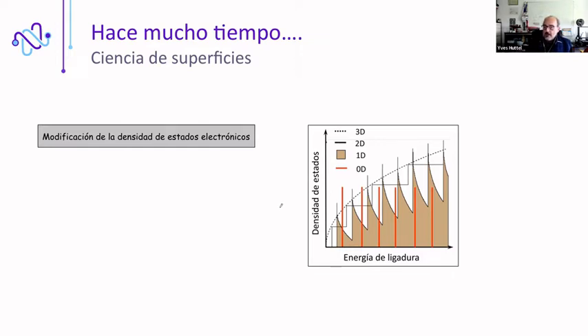And this is the key point, because as you reduce the size of your object, the density of states, which means the electrons that will participate in most of the properties of the materials, not only electronic properties, but also magnetic properties, optical properties, mechanical properties, will change pretty much as a function of dimension. That's why nanotechnology is so popular now, because we can make nanoparticles or other materials that have really different electronic states and different properties as a function of size.